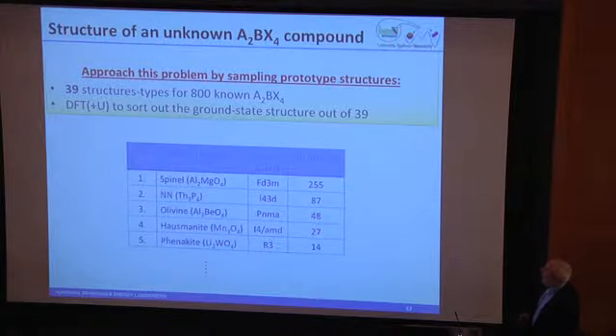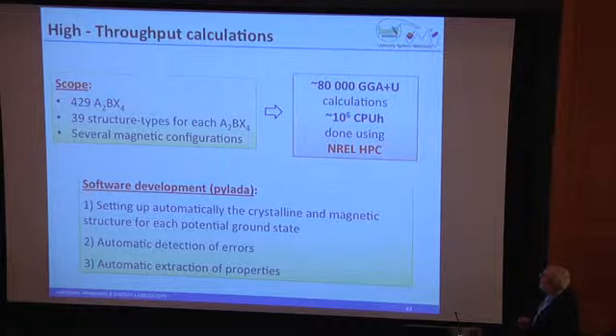So, for example, we want to sample prototype structures. So what we do is we do DFT plus U to sort out ground state structures out of 39 possible structure types. So, for example, I'll illustrate this with the spinels. We calculate those 39 structures, we calculate for every one of the possible spinels. And we look for what the ground state is. So this is not a small calculation.